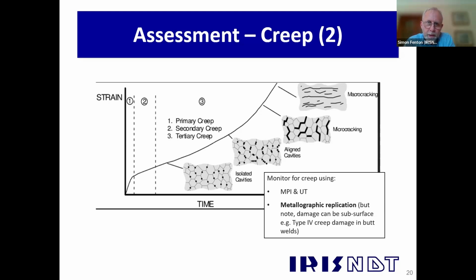UT, ultrasonic testing, is also really important because sometimes the creep damage can develop subsurface. So you're not always guaranteed to find the peak levels of creep damage at the surface. And this is true of things like butt welds and thick section components. So ultrasonic testing is also used as a key monitoring tool alongside replicas.